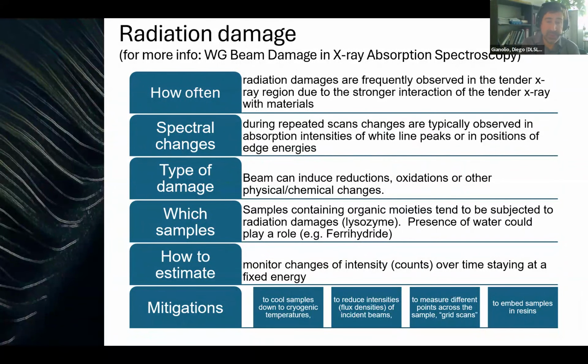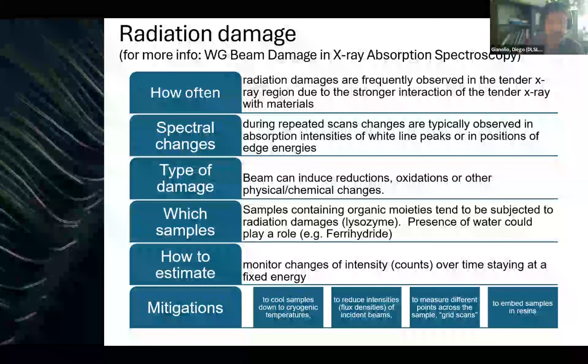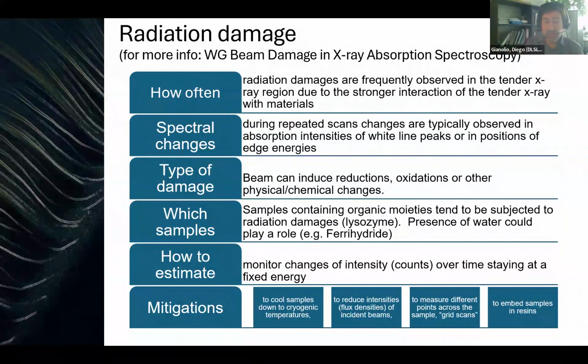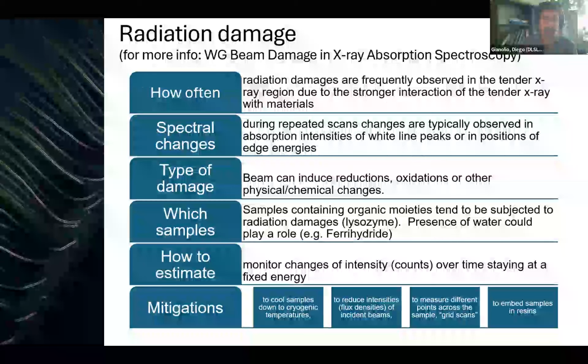And mitigations would be common mitigations that can also be used for hard X-rays, such as cooling samples to cryogenic temperatures, reducing the intensity, the flux of the beam, and measuring different points across the sample. And one finding that I think was due to some specific preparation for the tender X-rays was that embedding the sample in resin sometimes can help, maybe to prevent, for example, contact with water in the atmosphere.